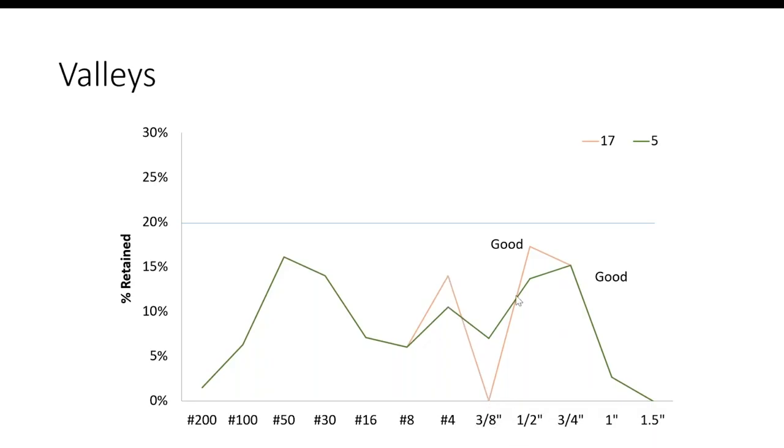We're gonna take all the 3/8 out. We're gonna take this one all the way down to zero. Watch. And it's still good. What? Now I'm not recommending this, but this is the key. See this 20% line? We never went over it. We never got too high. That's the key. Don't get too high, don't get too low.